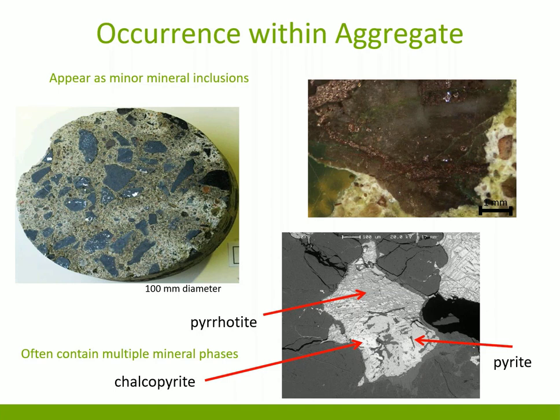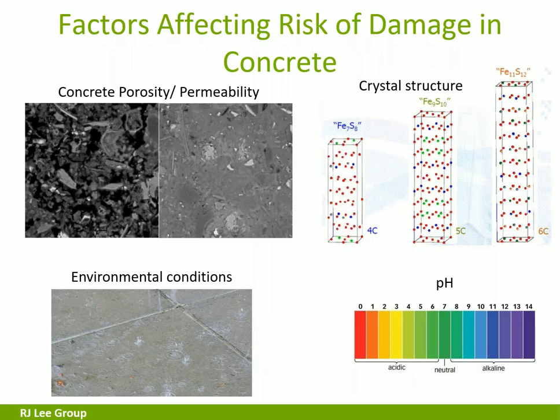There's a number of factors that actually are not fully understood of why this pyrrhotite can cause damage in one area and not so much damage in another. Some of the factors have to do with the quality of the concrete. If you have concrete with high porosity, which enables more air to get to it, you're going to have more damage. We're looking at the crystal structure of the pyrrhotite. The pyrrhotite comes in a number of forms, and some forms appear to be more reactive than others. Your environmental condition is going to matter. We are finding that the relative humidity does have a big effect.